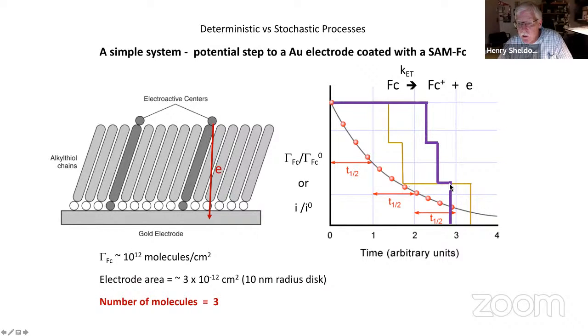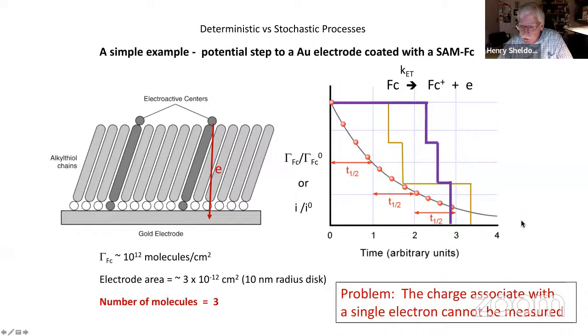Now, if you did the experiment, what I've shown you here is exactly how the system would behave. You would see step decreases in the concentration, but now you ask, well, what would the current response look like? And the answer is when the electron transfers, there should be a little current spike here. Should be a little current spike here. But of course, if you think about this, you can't measure that because you're talking about measuring the charge of a single electron, and that can't be done, or it hasn't been done in electrochemistry. Yeah, it's been done in physics at very low temperature, but not at electrode-electrolyte interfaces at room temperature.